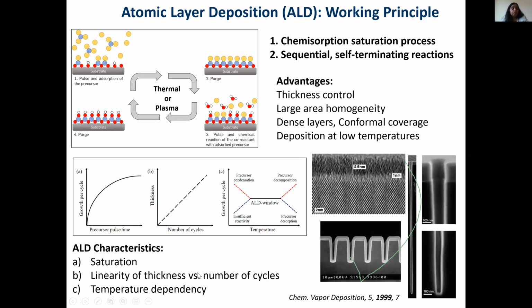Now, one particular feature of ALD is, as I said, thickness control. So imagine you pulse the precursor and purge it, then the next precursor, purge it, and you have a thin film formed in one cycle. When all the sites are covered, then the growth saturates. That means that you attain a state where no more growth is possible. Then you repeat the cycle. For every cycle, you can increase the number of cycles and increase the thickness. And then you have a linear dependence.